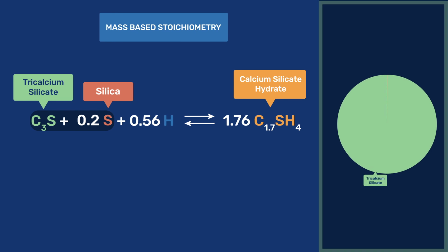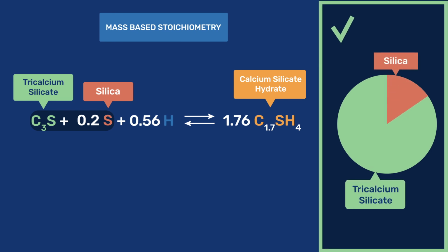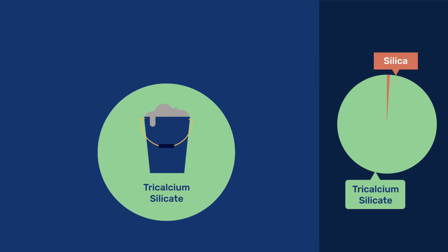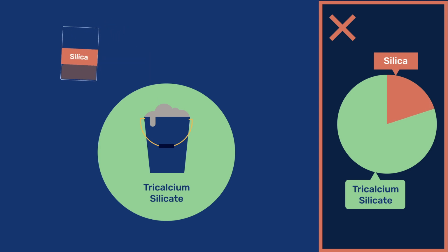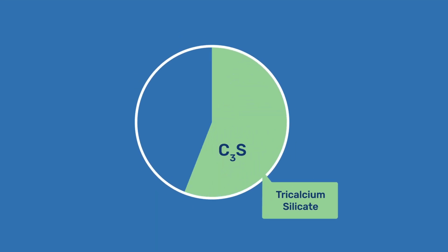So any amorphous silica exceeding 20% of the C3S in a blended cement will a priori not react. In reality, these limits are generally lower, as in addition to stoichiometric considerations, the slower reaction kinetics of pozzolanic SCMs poses another limit to the amount of material that can react in a practically meaningful timescale. We also note that in real cement, C3S represents 65 to 70% of the mass.